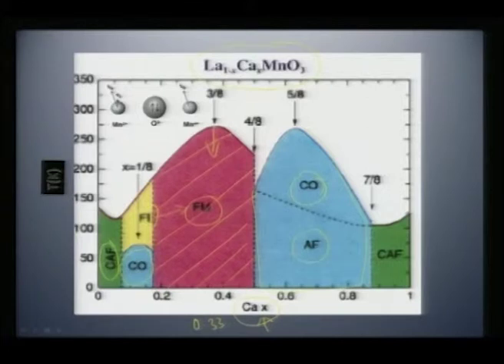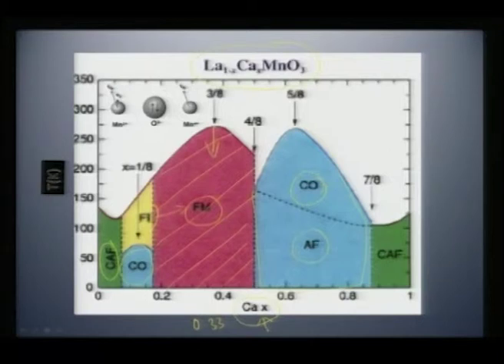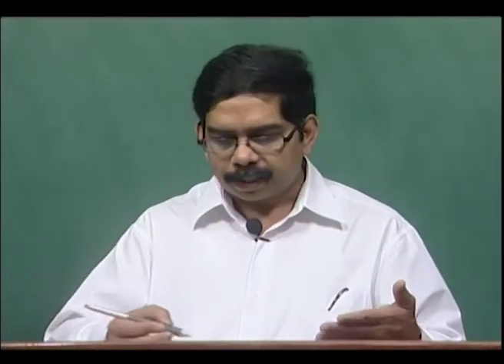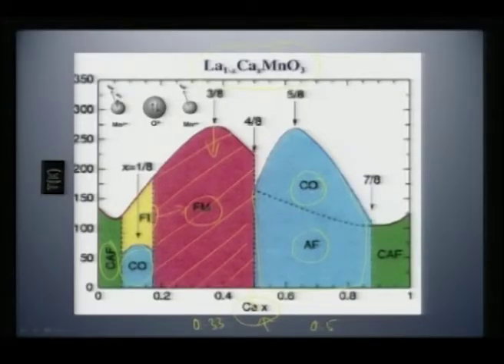So, the system does not necessarily remain in the metallic state for a long time. There is a critical composition which falls incidentally at 0.5. Beyond 0.5 there is still some amount of magnetic exchange, but it is all taken in a reverse direction. In other words, from a ferromagnetic it becomes an antiferromagnetic state, and it also shows an unusual charge ordered manganite state. So, in a simple system, if you keep changing calcium, you come across a variety of magnetic and electrical transitions.